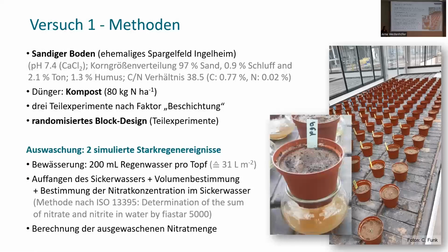During the experiment, there were two heavy rainfall events that were simulated. We gave a lot of rainwater onto the pot, and the leachate was captured, and the volume was determined, and the nitrate concentration in the leachate as well. And depending on the volume and the nitrate concentration, I could calculate the nitrogen that was washed out.